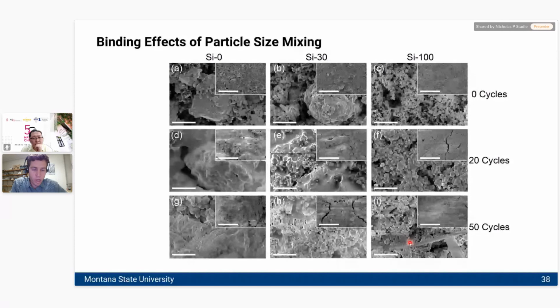But the problem is that what's happening here on the right is constant formation and reformation of this interphase layer in between the silicon and the electrolyte, and that's causing massive amounts of resistance to build up in the cell, even though the particle size is staying quite small. And so you want, to some extent, the properties of a large particle, but you want that particle to stay in contact. I think what we're seeing here in the middle is that large particles of micron-sized silicon are being held together by small particles of nano-sized silicon. Even though those large particles are coarsening and amorphizing over lithiation and delithiation, they're staying in contact because of the nanophase particles that are stuck and acting almost as a binder in between the large particles in the middle.